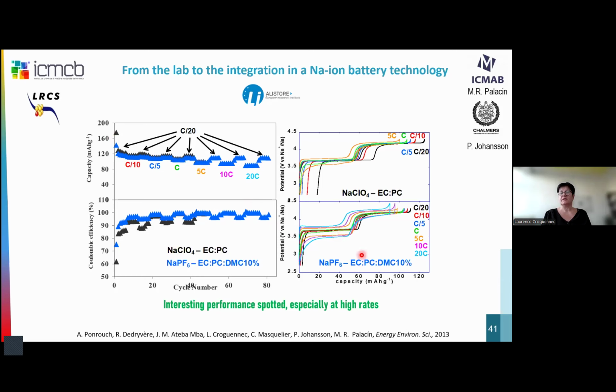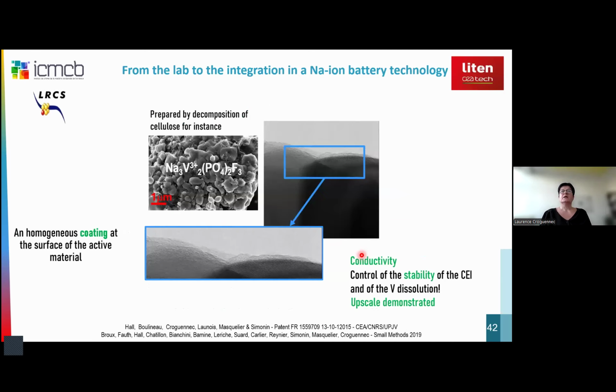And I would say that we were able already at that time to improve the performance, changing the chemistry of the electrolytes. So then we merge effort with Liten in order to do the upscale of these materials, and especially to be able to promote the formation of these materials with a controlled carbon coating at the surface.